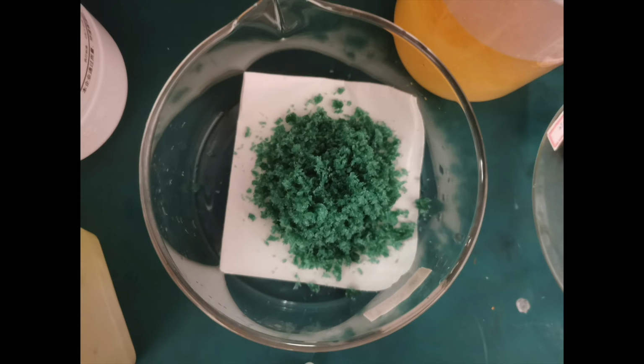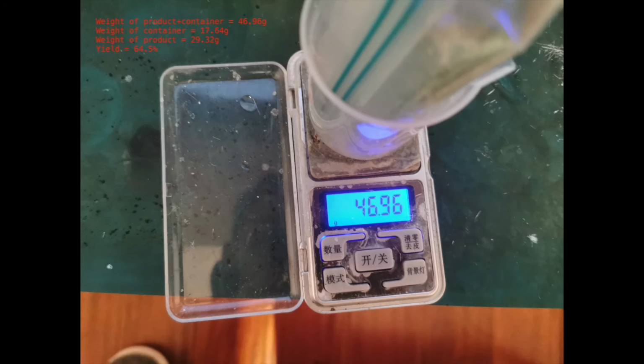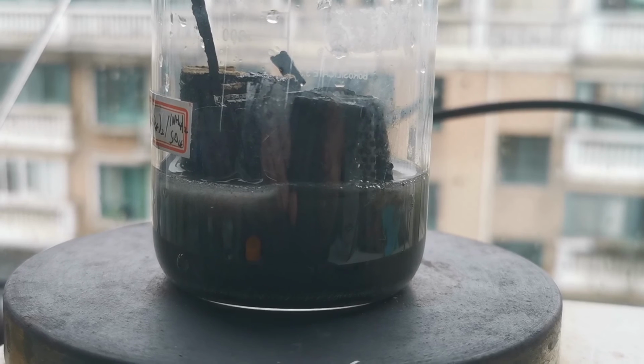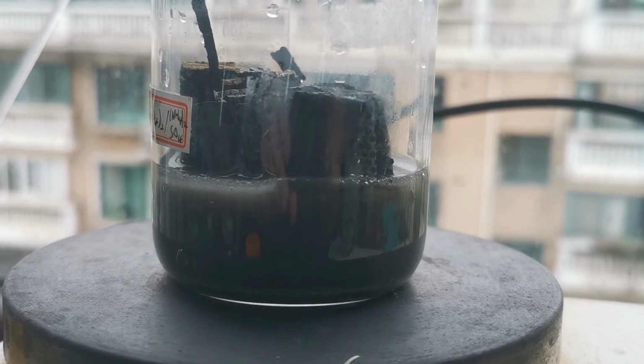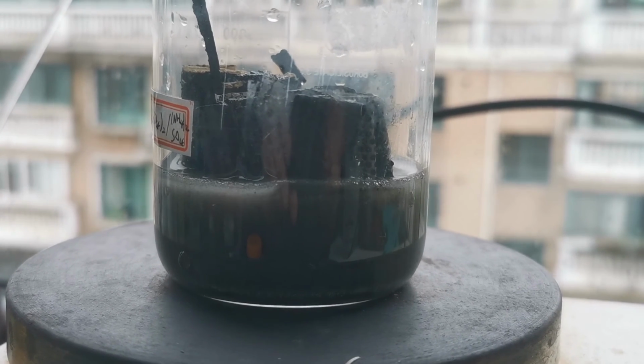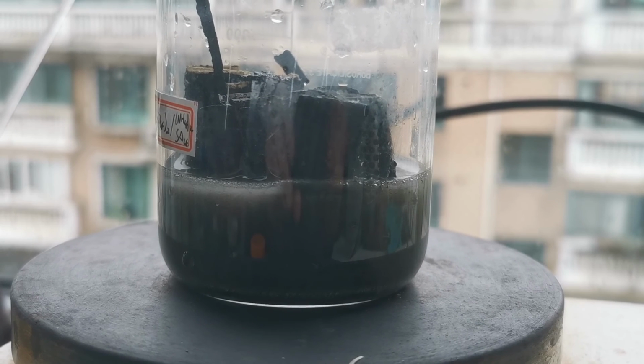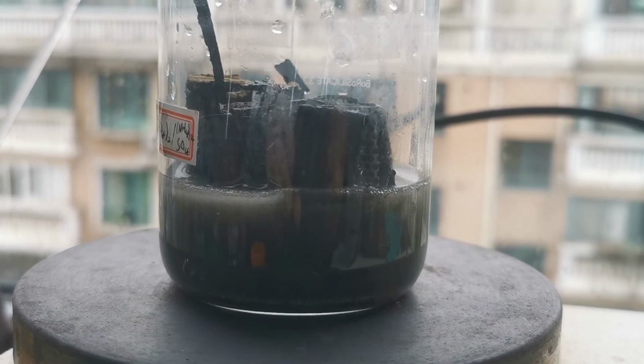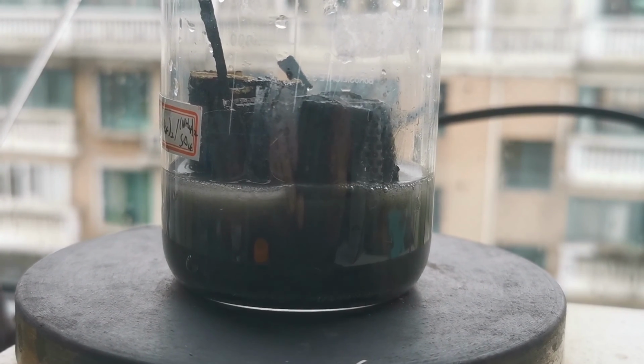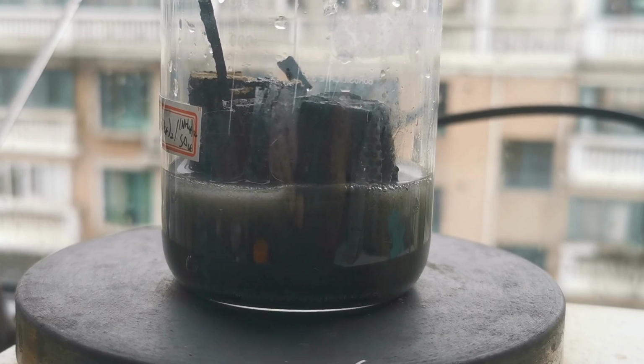The final yield of nickel sulfate heptahydrate is 29.32 grams, representing a yield of 64.5% with reference to the 17 grams of nickel hydroxide dissolved in the acid. There is still some nickel in the mother liquor, but unfortunately I spilled it on my lab table, so never mind. Still, I'm totally satisfied with the amount of product that I have, and I'm now ready to perform some experiments such as electroplating with it.